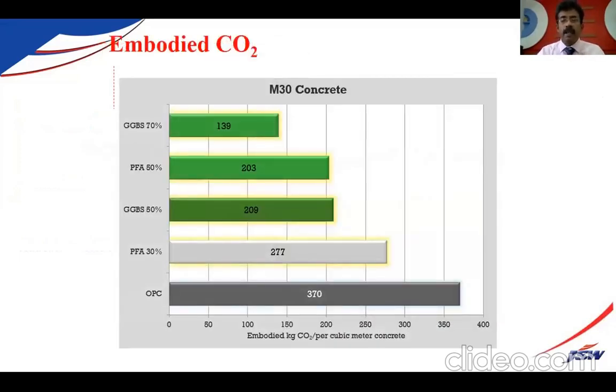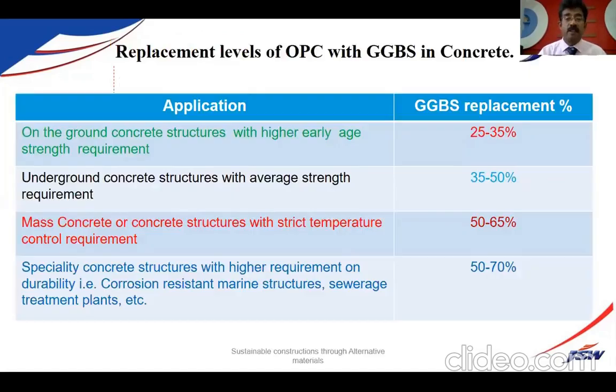So there is a chart which shows how the embodied carbon dioxide emissions can come down using various percentages of fly ash and GGBS. OPC is 370 kg per cubic meter. If you use GGBS up to 70%, it is 139 kg. So this is the CO2 emission reduction using secondary cementitious material like slag and fly ash.